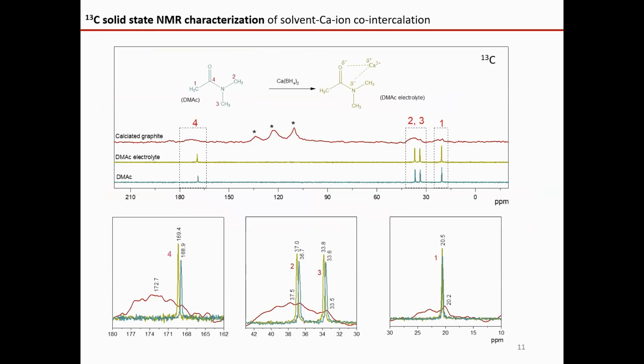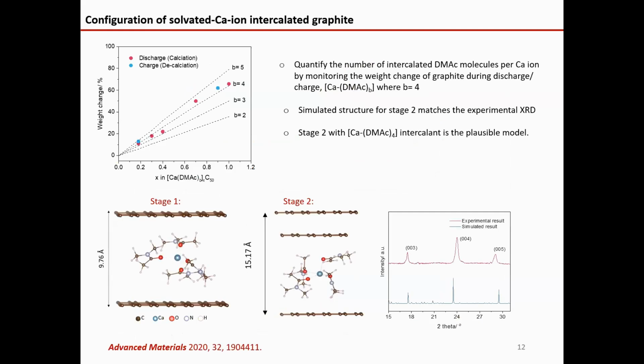So next is where the calcium ion is intercalated into graphite. We conducted the NMR characterizations. We can show that after the calcium ion is intercalated into the graphite, the carbon spectra slightly shift. That means the DMAc solvent is also intercalated in graphite.